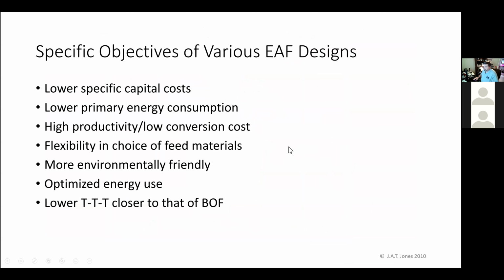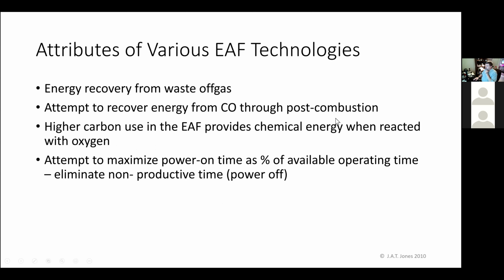So some of the different objectives of various furnace designs were to lower capital cost, lower primary energy consumption, achieve higher productivity or lower conversion costs, flexibility and choice of feed materials, more environmentally friendly, optimized energy use, and tap-to-tap times or cycle times closer to that of a BOF. So a BOF can typically process a heat of steel in anywhere from 25 to 40 minutes. And so that became the goal for electric furnaces. And we have some now that are capable of completely producing a batch of steel in 30 minutes. Probably on average, most people are between 50 and 60 minutes these days.